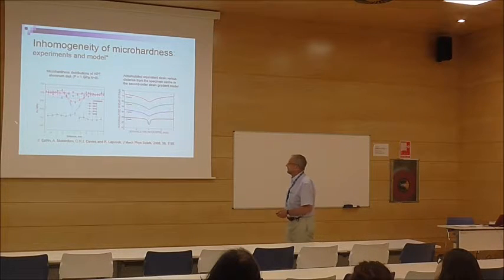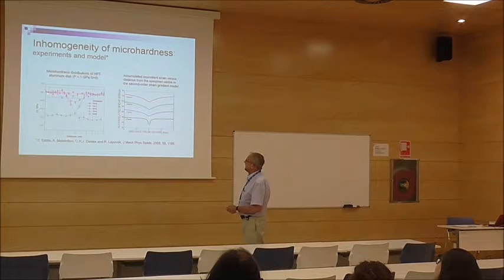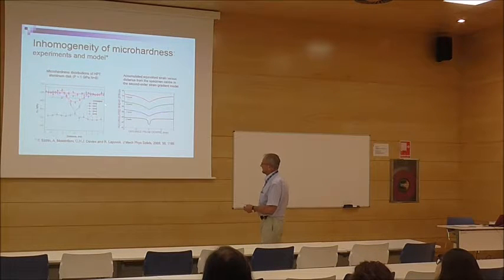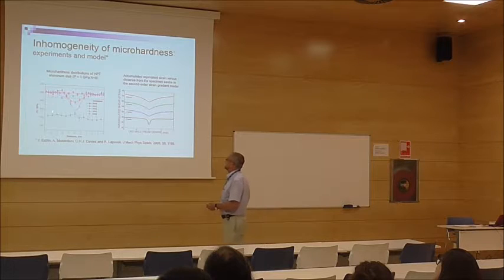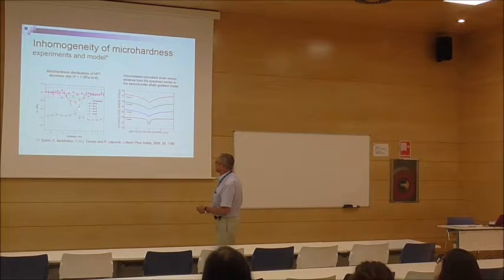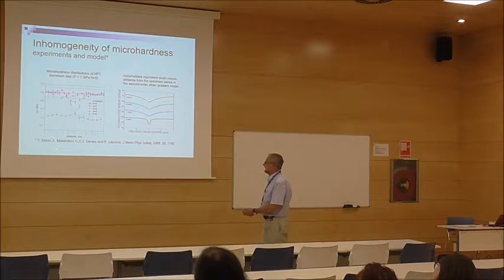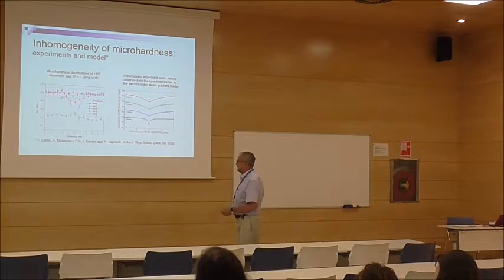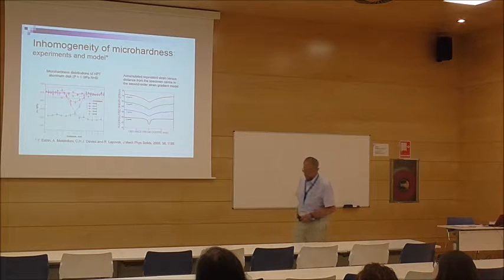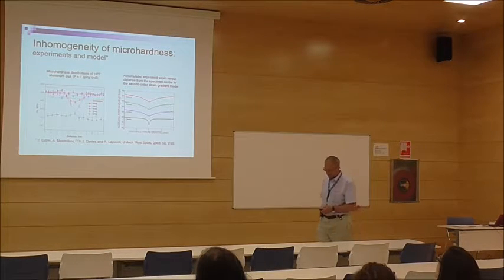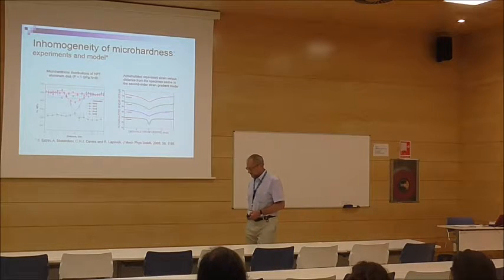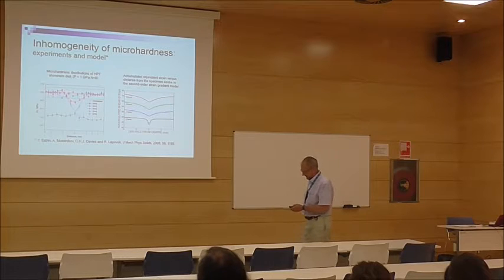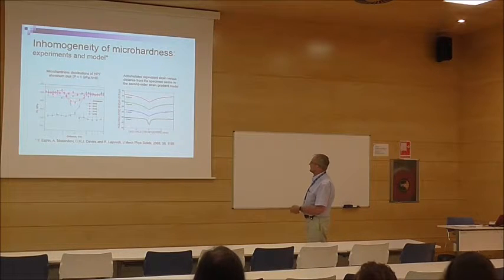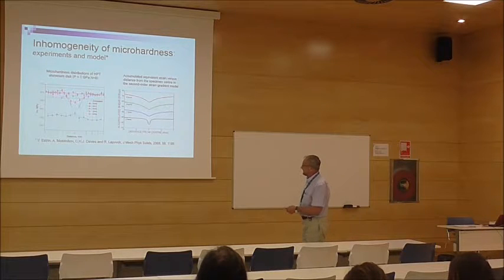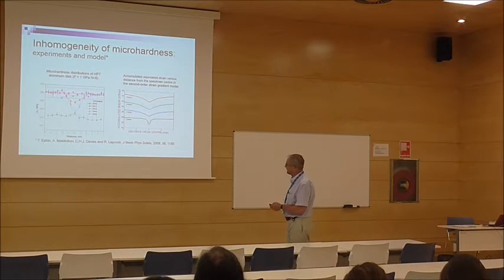So when we checked with aluminum 1050, we found that after n equal 1 the homogeneity improves significantly, and after rotation, at n equal 6, it will be just a straight line within error. It's the same, and Yuri Estrin and Dmitri Molodov with co-authors made a calculation, and they show with a model of straining that you can predict that the gap in the center will disappear with the number of turns.